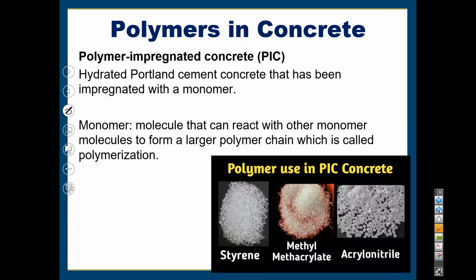And then once you have the water out, then you impregnate it with these monomers, whether it's a full or partial impregnation. You can do it through liquid or gas. Liquid is the most often used, where you dip this piece in the monomer that's in a liquid. Very similar, some of you do pipe or forms, where you take the forms and you dip them in the form release in a dip tank. It would be kind of like that. You take the concrete piece, dip it in a dip tank, either partially or fully, to get the monomers to soak into these voids.